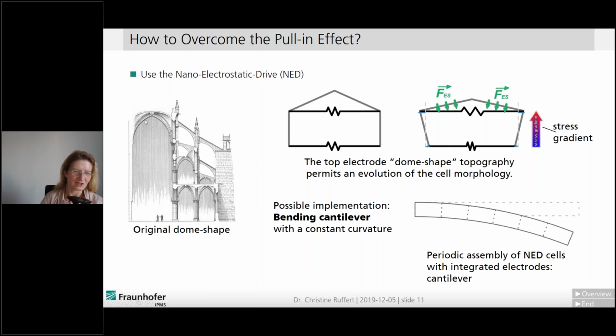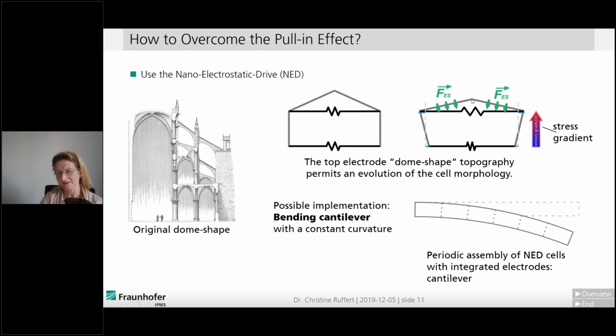Consider a dome-shaped structure, like here on the left-hand side, like from a church, and we adapt this shape for the upper electrode, as you can see in the sketch in the center. So the top electrode is shaped like a dome or like a roof. With this topography, I will explain what happens. The upper electrode will bend down, or try to lower the distance to the bottom electrode, but this is not possible in this configuration. What happens? The side walls on the left and right-hand side will tilt and cause a stretch here, and will cause a tilt here.